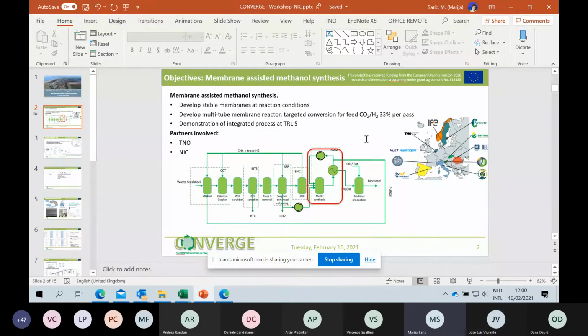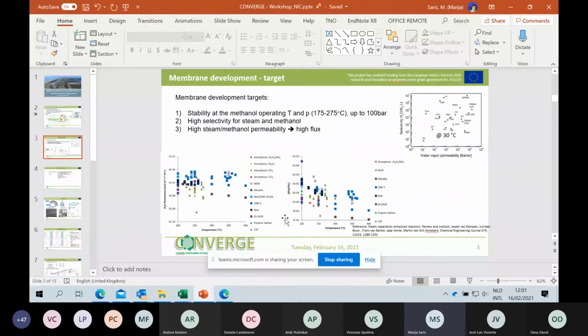Okay, so the specific goals for this work package are to develop stable membranes at reaction conditions for methanol synthesis, and develop a multitubular membrane reactor with the targeted conversion of feed CO2 and hydrogen of 33% per pass. Typically in the industry we have around 20%. So in this way, we can decrease the recycle, and in this way decrease the reactor size. And we also want to demonstrate this technology and integrated process at TRL5. And partners involved in this work package are TNO and others. So as we said, we set membrane development targets.